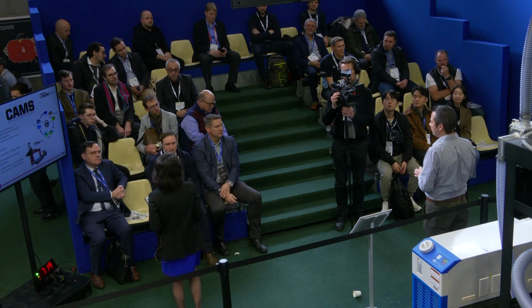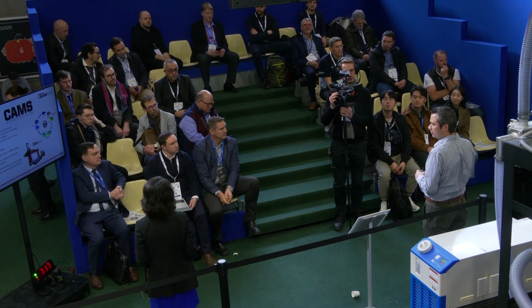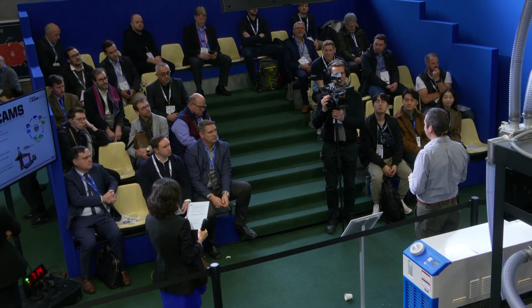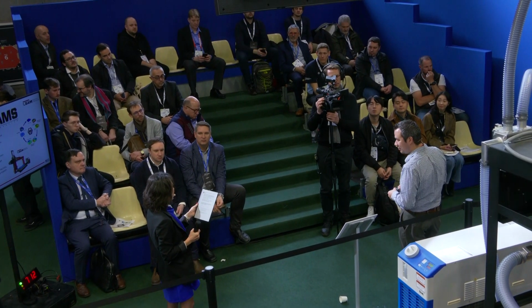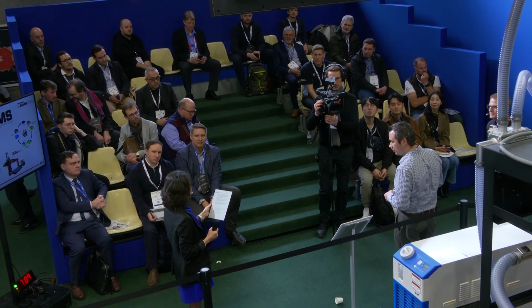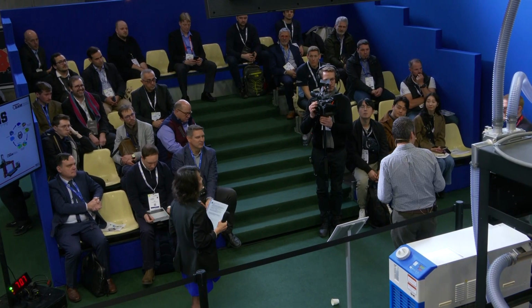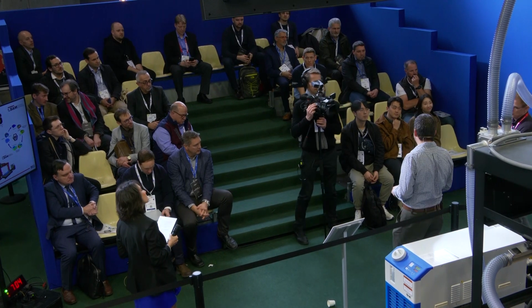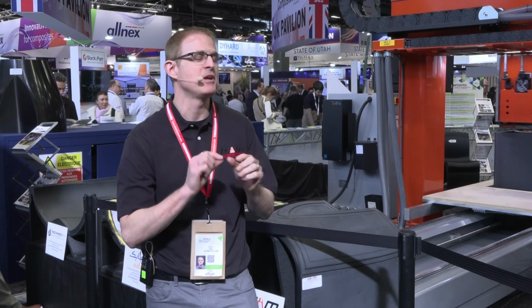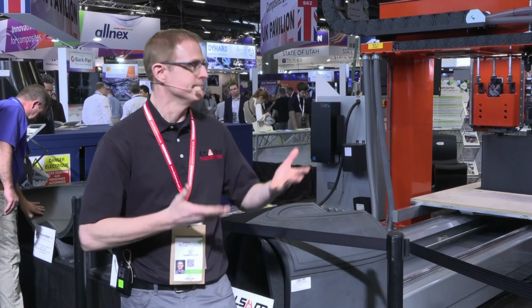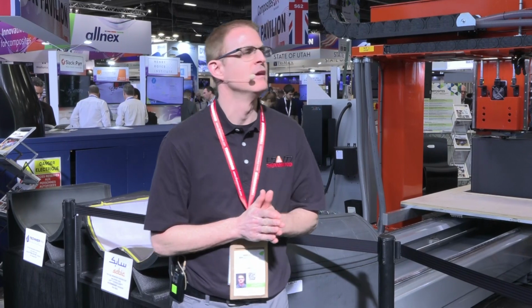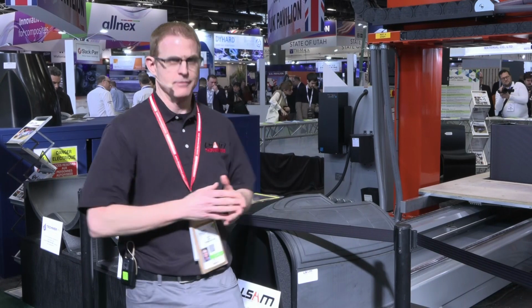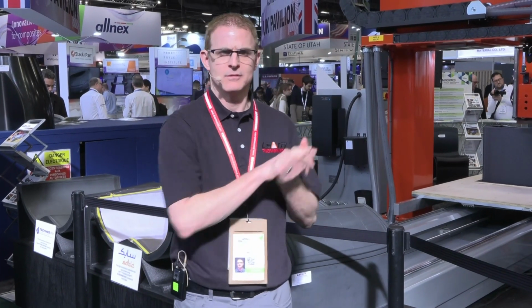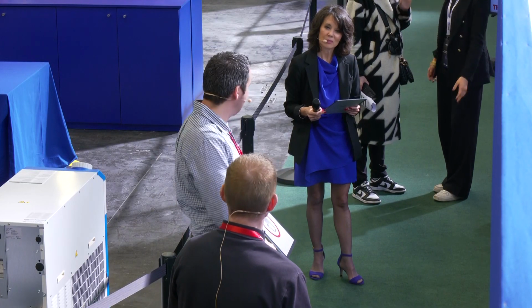Okay, I have a question for Scott. What is the typical print bead size on an LSAM? The typical bead size is 0.83 by 0.2 inches, which would be 21 millimeters by 5 millimeters. It's capable of printing pretty much any bead size, but that is the optimal bead size to retain the heat that's needed to get the good bonding that we need with the system. Okay, thank you.